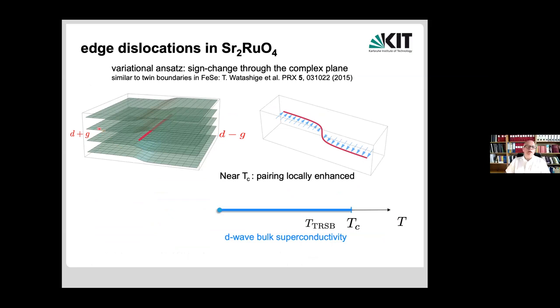Okay, there are two ways. Either you are near the dislocation, and you don't need to be in this very plane, because in all directions this strain decays like 1 over R, with a sign change along the Z direction here. So if you go up here from D plus G to D minus G, you would still have the same situation. If you go even further away, then the problem is moot because there's no G anymore. Right. Yeah. Got it.